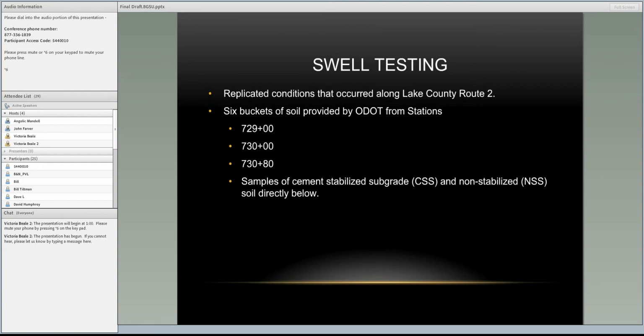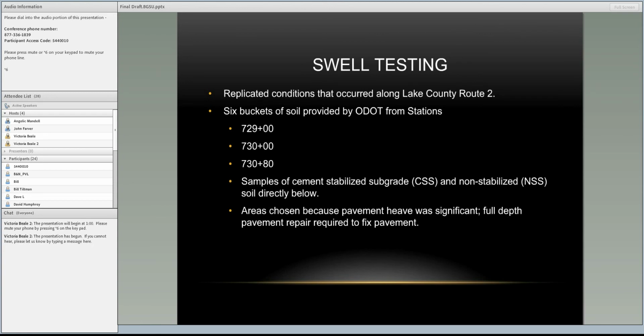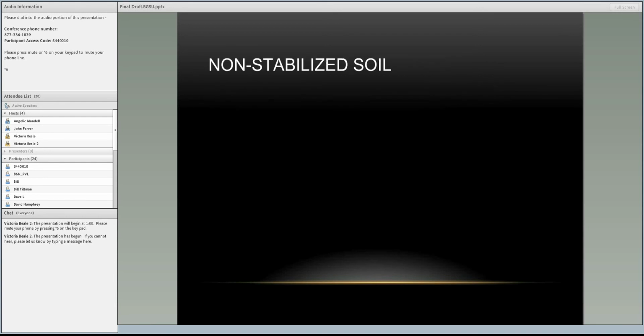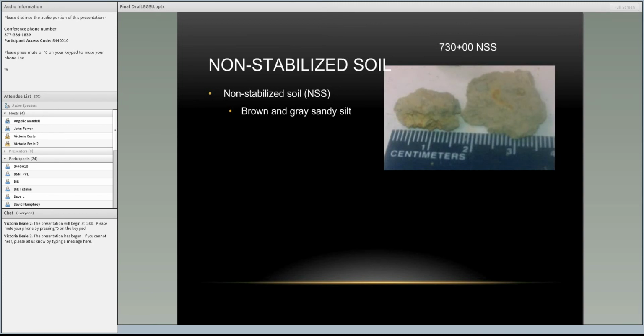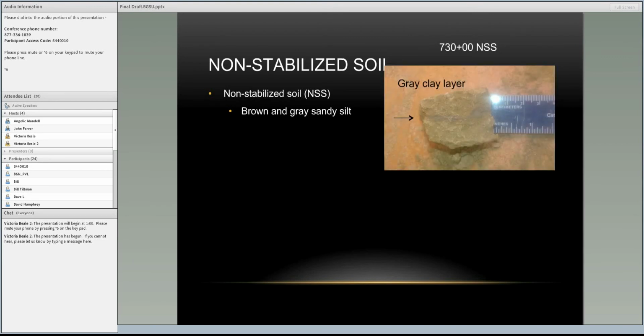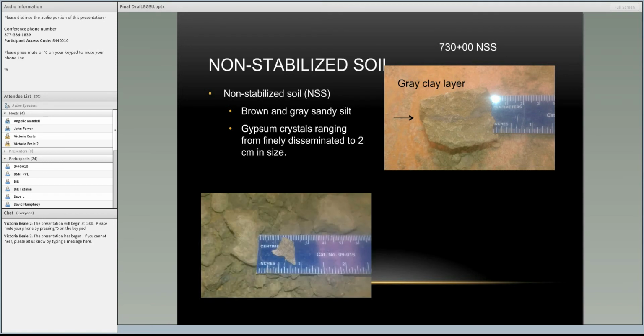First, we wanted to characterize the non-stabilized soil. And what we found is the non-stabilized soil is primarily brown and gray sandy silt. And you could visibly see a lot of clay in the soil. It might be hard to see on this image, but there is a gray clay layer running through the middle of that sample, and that was very common in the non-stabilized soil. There was also a lot of gypsum crystals. They were finely disseminated and also very visible to the eye, up to 2 centimeters in size. And we also saw a lot of black shale as well, as small as a couple millimeters up to a couple centimeters in size.